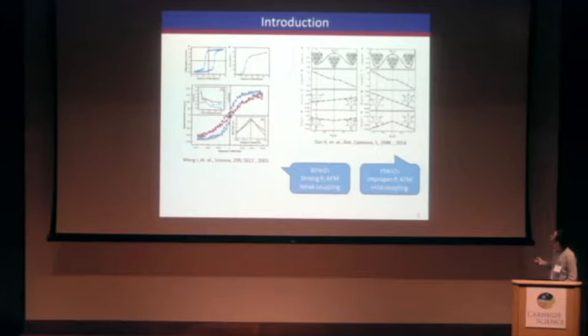Another example of a multiferroic is yttrium manganite. It is known for improper ferroelectricity, where the polarization is induced by the primary order parameter, the K3 mode, the tilting mode, and also the non-collinear antiferromagnetism from the geometrically frustrated antiferromagnetism. The coupling between the polarization and the magnetism is a little bit stronger. The two quantities are mediated by the K3 mode.